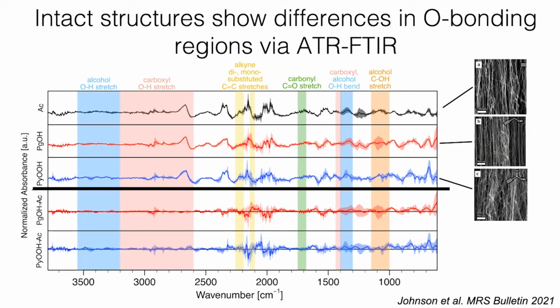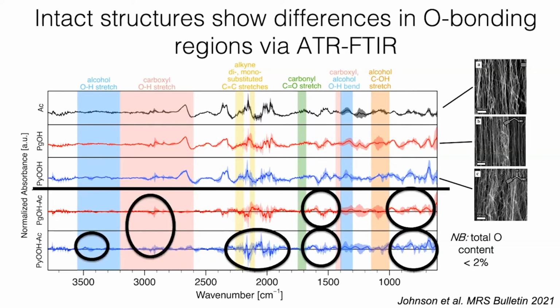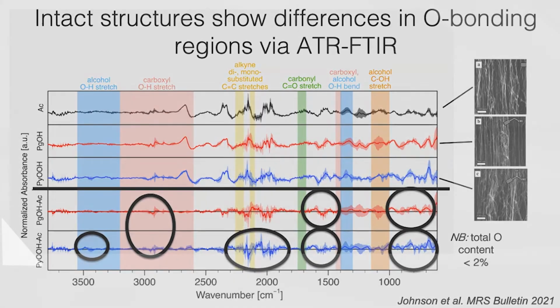I've marked the 0 point in a light black line around each of these. So anywhere where you see that red wiggle in the bottom part of your screen deviate from center, and so you can see white space, that's a place where there's a real molecular feature that persisted in the replicates in this experiment. And the same thing for the blue. And what we start to see is that there is oxygen functionality persisting in these nanotube structures exactly where you would expect. You see an alcohol stretch for the propiolic acid fed nanotube groups. You see a carbonyl stretch, especially in the nanotubes that are grown from this propiolic acid.